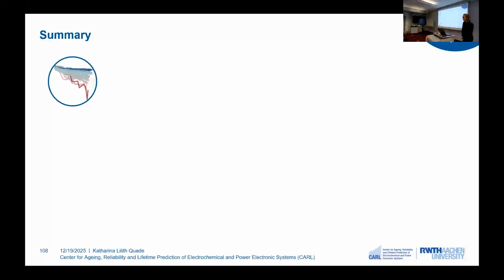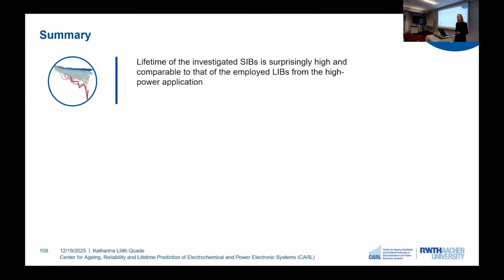So let's summarize my overall work. In my work, I have developed and applied experimental, model-based, and also data-based methods for the rapid integration of sodium-ion batteries. In the first chapter, I presented an experimental aging study of early commercial sodium-ion batteries, and we saw quite a remarkable lifetime behavior. We could also see that, especially for the lower SOC region, mechanical degradation might be a problem. However, for our use case, this is not of a very high relevance because we're always cycling in the mid-SOC range where we really have minimal capacity fade.